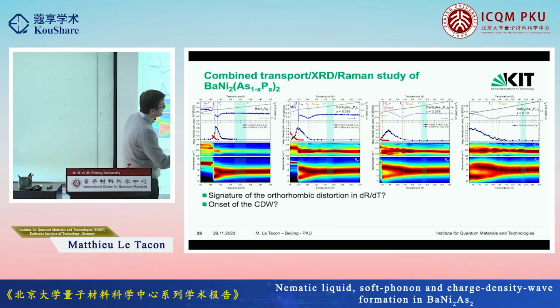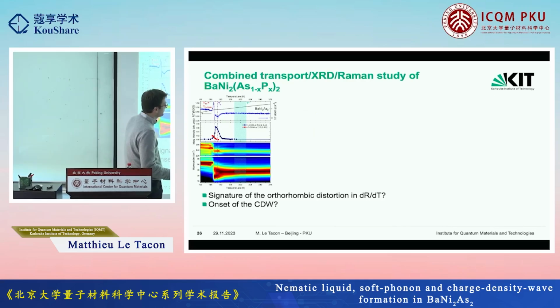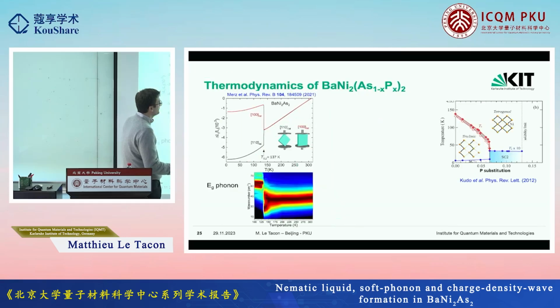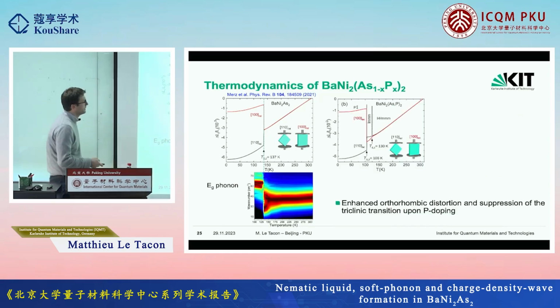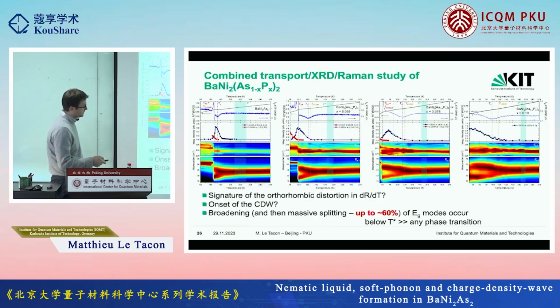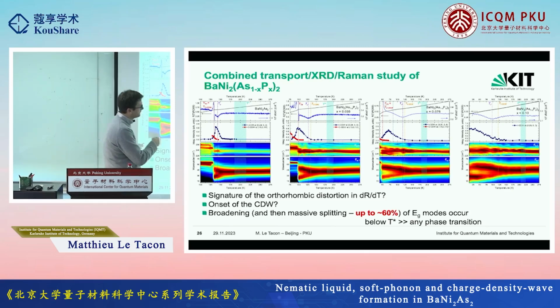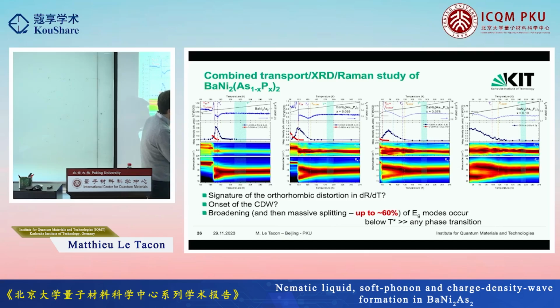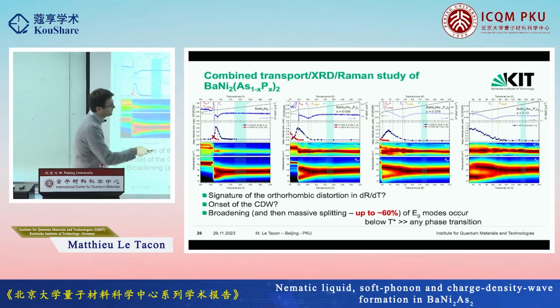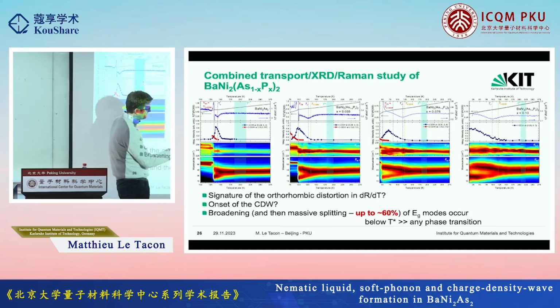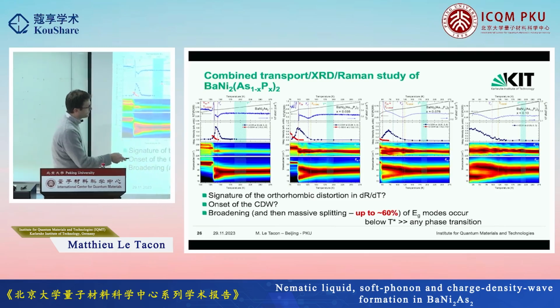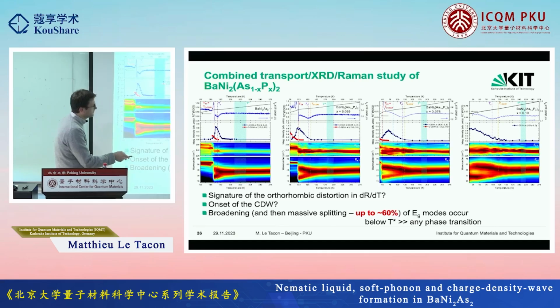So, and if you see this one, the 10%, you're basically outside. I have troubles with this one. Okay, sorry. So with the 10% dope, we are here. So there is no structural transition anymore. And yet you see this nicely, this splitting. So the higher energy mode, the splitting is more subtle, and is actually more seen as a broadening, at least at the low doping. And here it mostly looks like a broadening, but harder to see to resolve two peaks. But we nicely see, at least in the lower and the higher doping, and down to the lowest temperature, we have this completely lifted degeneracy.